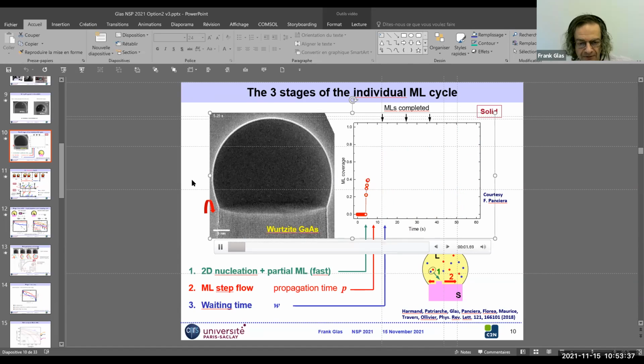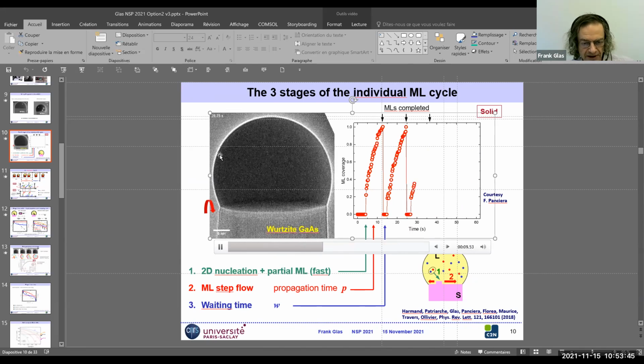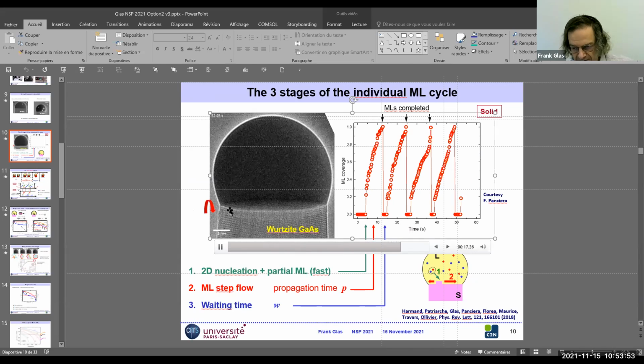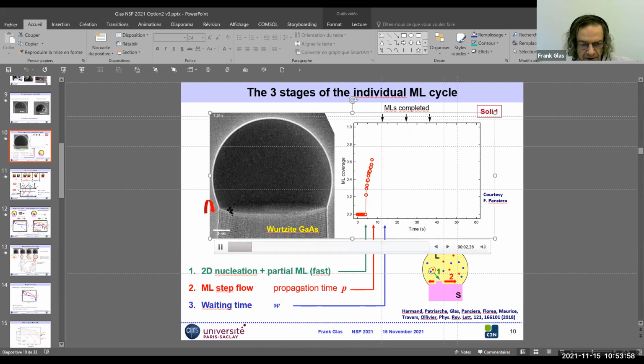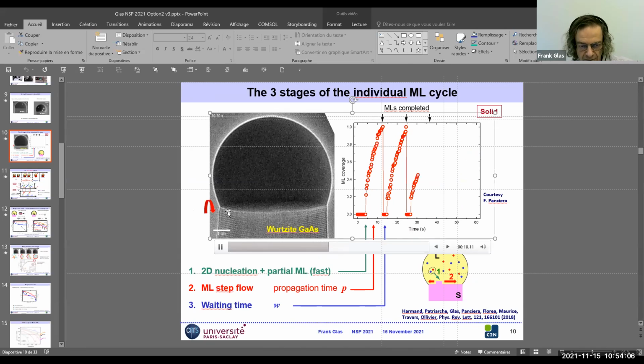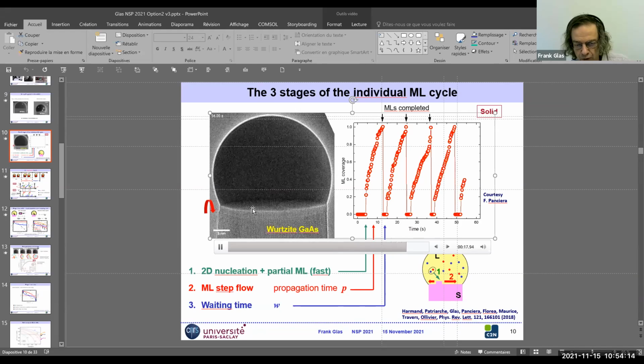Yes, for the zinc blende phase, the situation is very different. It's something we've been working on also with Vladimir and discussed with Jerry Tersoff. The very different thing is that the interface is not flat, so the interface is truncated. And I think in this audience, we all know that this means that the monolayer grows probably by using atoms from the liquid, but also because when the monolayer forms, the truncation gets deeper, then there are atoms which are transferred from the already grown nanowire to the monolayer.